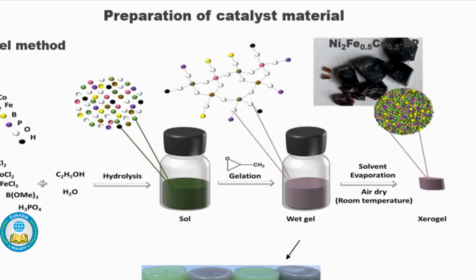Now the precursors were added into a mixture of ethanol and water for hydrolysis to take place. After propylene oxide was added into the mixture, the gel was formed in less than 5 minutes through the formation of metal-oxo-metal bonds, and the gel was allowed to age for 24 hours, then dried in air at room temperature, and a glass-like dense gel was formed.